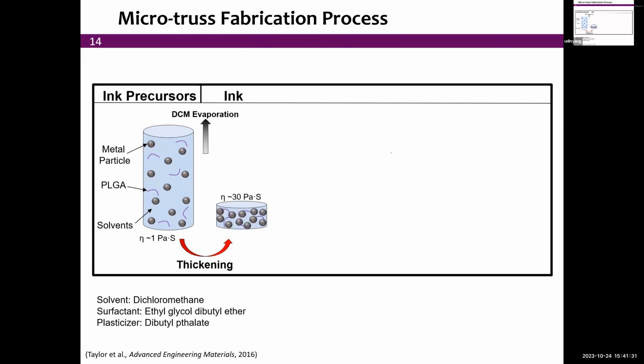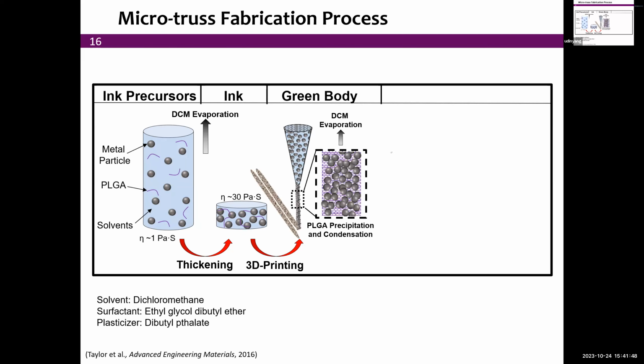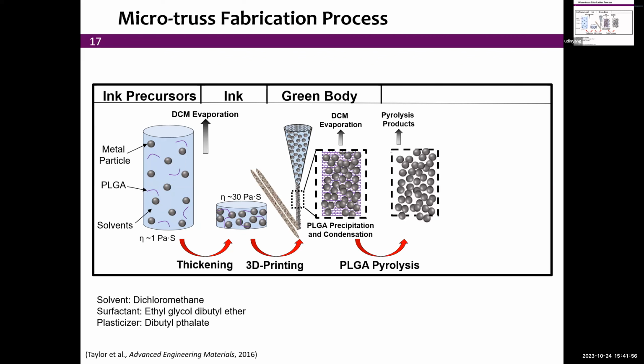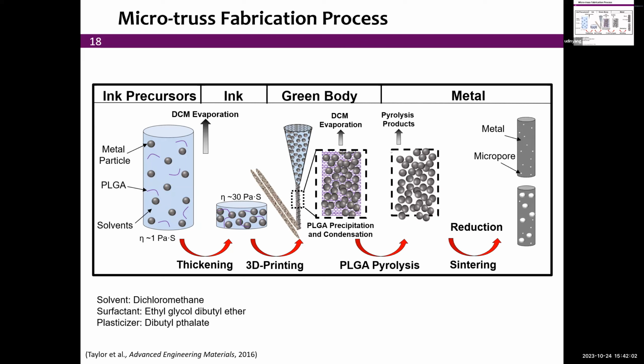We then thicken this ink to the point where it's typically almost the viscosity of honey, and can still be extruded through a nozzle, where you now 3D print at room temperature in air those loaded inks, and then you further evaporate the solvent. So now you precipitate the binder that becomes a polymer matrix that contains the particles, and you pyrolyze, so you burn out the binder. That's where the first level of shrinkage happens. And then if we have an oxide, we reduce it with hydrogen and then sinter it to metal. So that's in principle the manufacturing path for those structures.